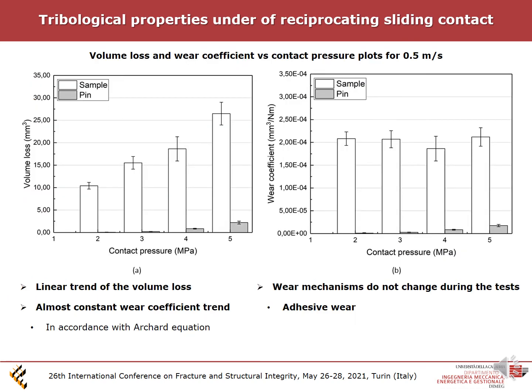Nevertheless, in these sliding conditions, Stellite-6 coatings exhibit a linear trend of the volume loss, as shown in the present slide, and therefore an almost constant trend for the wear coefficient, that is in accordance with the Archard equation.